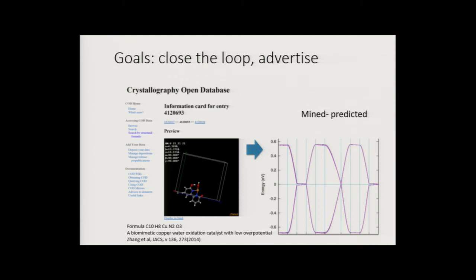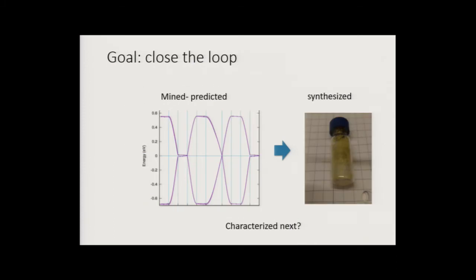We don't know exactly what it would look like. So here's an example. We mined some of these materials for very simple Dirac crossing points. This material was first synthesized in 2014 for totally different purposes. It is a biomimetic copper water oxidation catalyst, but it has very interesting band structure properties, a Dirac crossing point with a flat band. We spoke to the organic chemists, they synthesized some vials, and the idea is that we're looking for somebody who can help us characterize it, or the other way around.